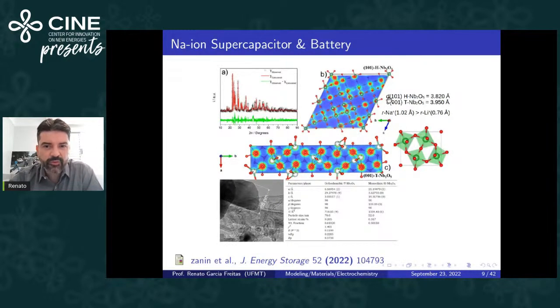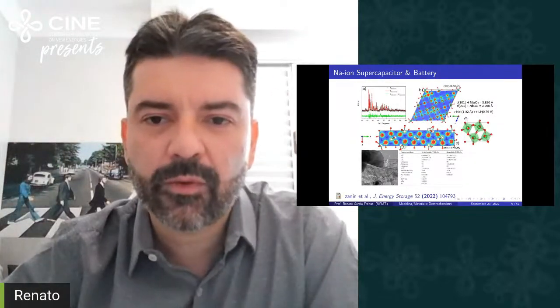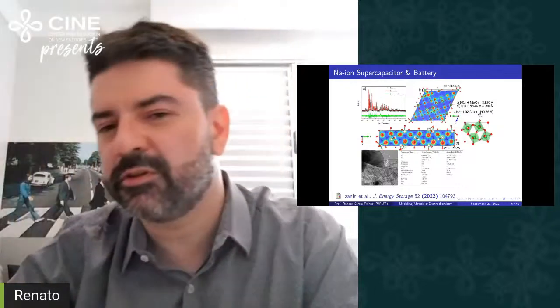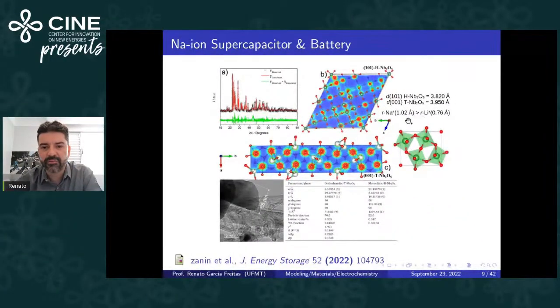The interplanar distance for 101, which is monoclinic niobium oxide, is 3.8 angstroms, and the lattice of the 001 orthorhombic niobium oxide is 3.9. So we have an increase, from 3.8 to 3.9 in the lattice plane from 101 to 001, and it's important because of the Stokes radius of sodium, which means sodium with water molecules, which is a little bit larger compared to lithium, which is the most studied, isn't it? Many batteries nowadays are studied using lithium. So the radius for the sodium ion is 1.02 angstroms, which is larger compared to the Stokes radius of lithium, which is 0.76.